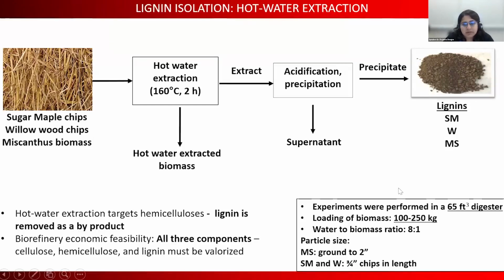All these experiments were conducted at pilot scale in a 65 cubic feet digester, and the loading of the biomass was about 100 to 250 kilograms. The water to biomass ratio was 8:1, and the size of the biomass differed depending on whether it was miscanthus, which is a grass, versus wood chips of sugar maple and willow.